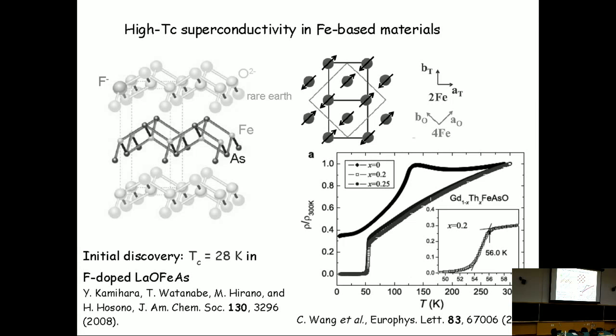So as I mentioned, superconductivity was originally found at 28 Kelvin, and later on in the gadolinium iron arsenic oxygen doped with thorium, they got the maximum Tc in this bulk system of about 56 Kelvin for doping of 20% of thorium. It's interesting to note the following: when you don't have any kind of doping at all, the iron layers order antiferromagnetically. They have a stripe antiferromagnetic order that I can draw in here. So in one direction, the nearest neighbors order ferromagnetically, whereas in the opposite direction, the nearest neighbors order antiferromagnetically.